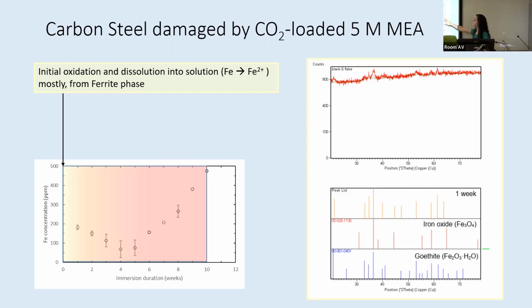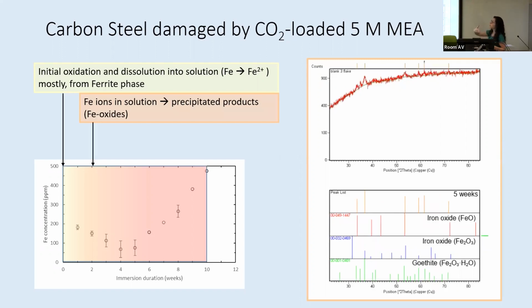We do have some solid precipitation, a very minor amount, and we can establish that that's an iron oxide of one of two types that we've got depositing on other surfaces. Then as we continue in terms of weeks, we see a decrease in the iron ions in solution. What's happening during that process is an increase in the precipitation of iron oxide products. So obviously this is a point where we would see less iron in solution, an interesting point for us to consider in terms of the impact of that iron in solution on degradation pathways, etc.